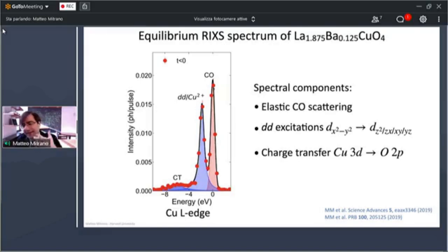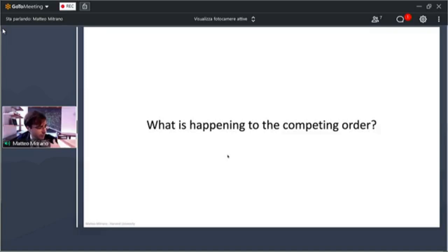Before I start discussing the dynamics of this spectrum, let me just tell you that there are 3 dominant spectral components that one has to take into account. Here we are looking at the material at equilibrium, and we have one elastic feature that corresponds to the diffraction of this charge density wave modulation. We have then 2 inelastic features related to so-called dd excitations. These are excitations between the orbitals, and charge transfer excitations that correspond to really charge transfer between copper and oxygen orbitals. Now, what we decided to do is that we performed the study in which we excited the material with strong laser pulses and followed the behavior of this competing order at finite momentum in the charge sector.